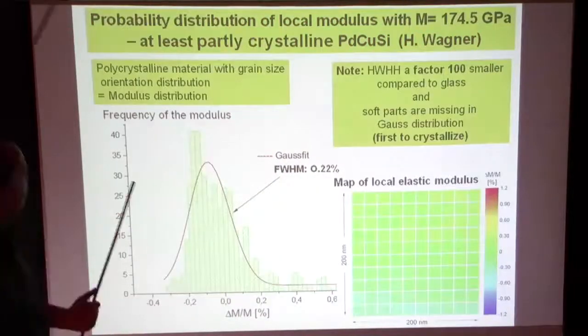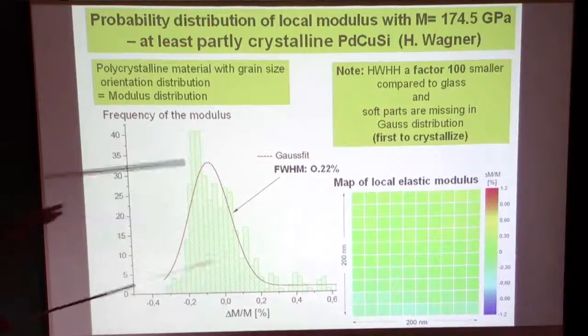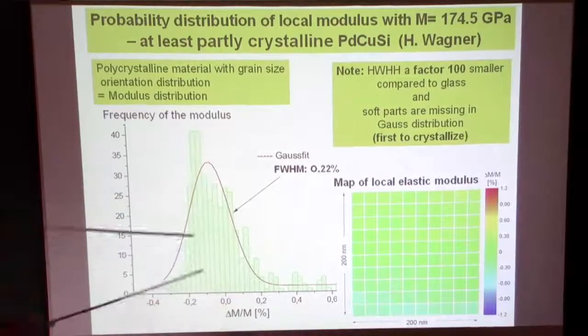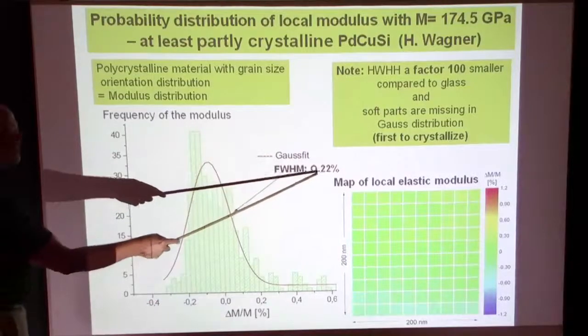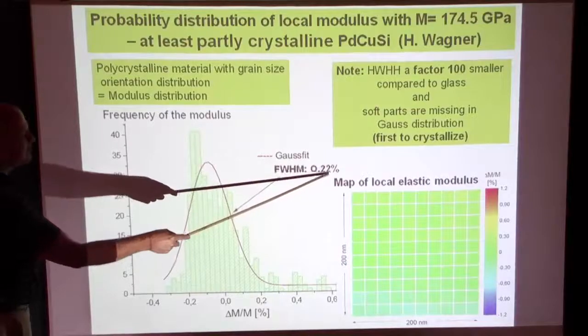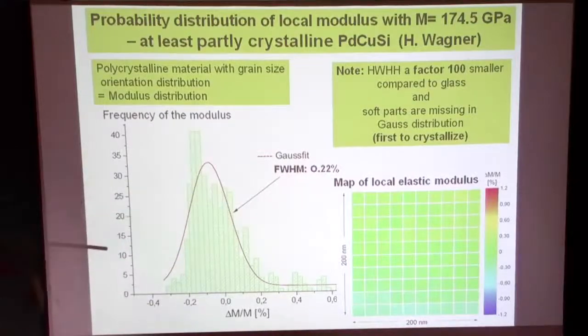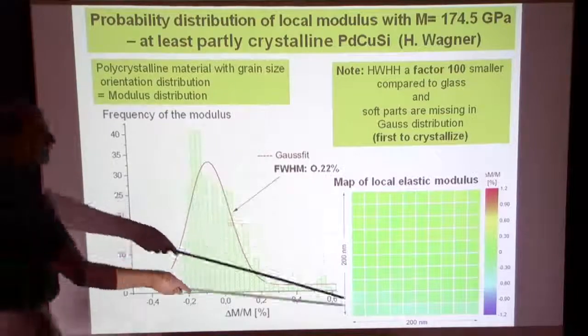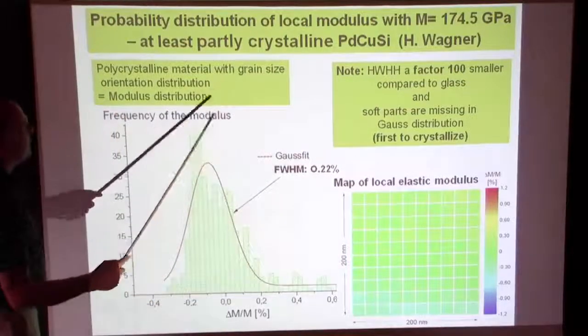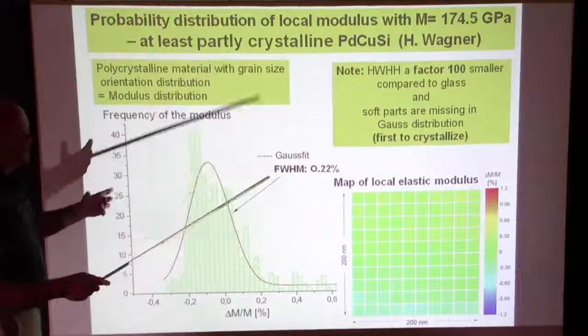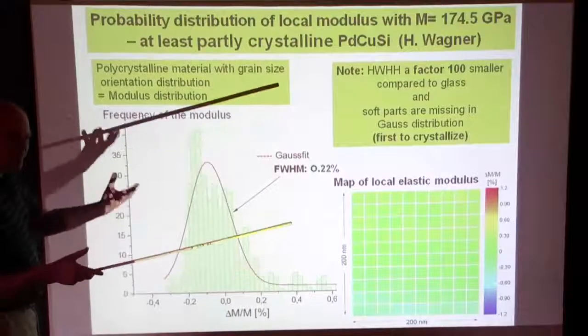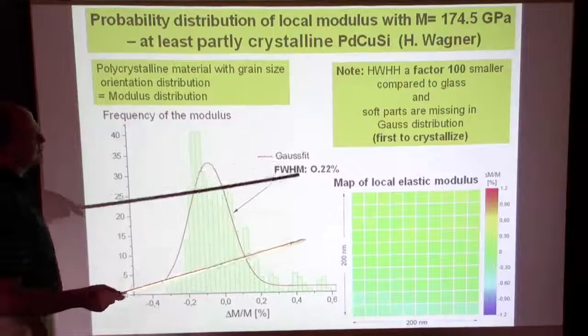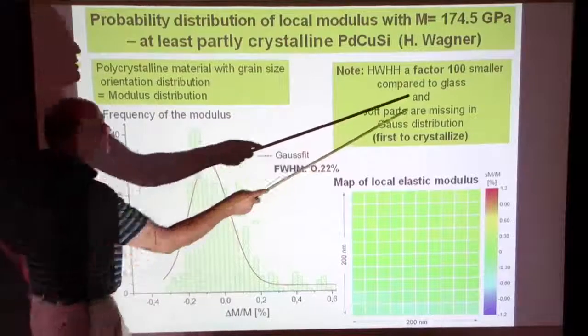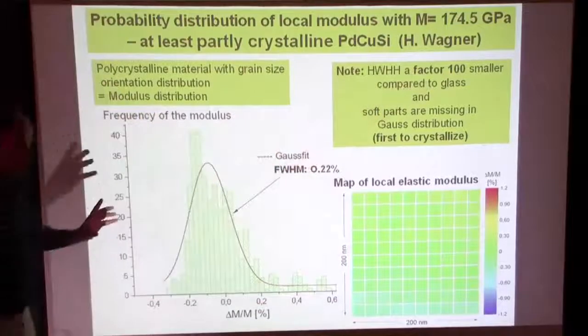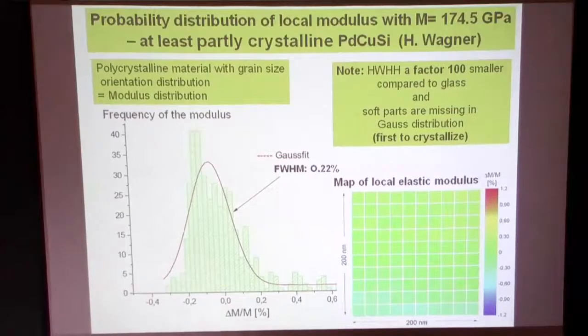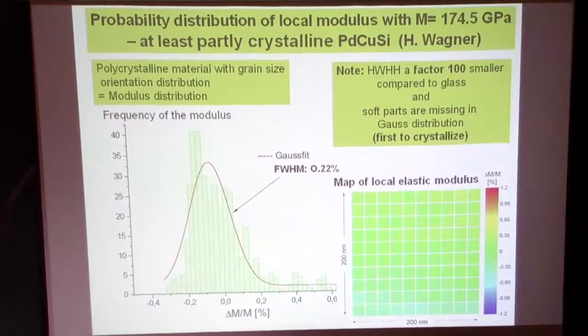And if you crystallize it now, just use this material, crystallize it now, do it again, and the width actually goes down to 0.22%, which is in the order of our resolution of the measurements actually, and the map looks very homogeneous. We have to be careful. If you crystallize this material, it shows different orientation of the grains. You have to measure in one grain, otherwise you have different crystallographic orientations. But at least there is a factor of 100 smaller compared to the width of the distribution. The width of the Gaussian distribution shrinks dramatically.